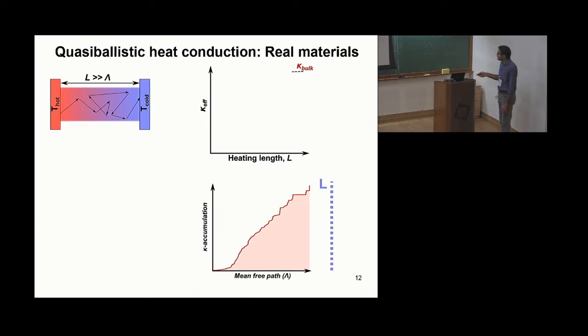Essentially, phonons with mean free path up to, say, this value, contribute so much to the total thermal conductivity. Now in the diffusion regime, when L is much longer than lambda, you typically have L sitting over here, and experimentally you measure the total accumulated value. In an experiment, you measure the contribution from all phonons, which means the thermal conductivity you measure here is equal to this accumulated value. Because L is much longer than any lambda in the material, you measure the total bulk value that we all know for any material.